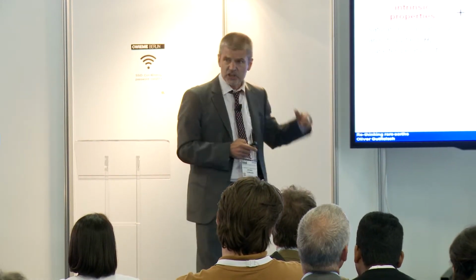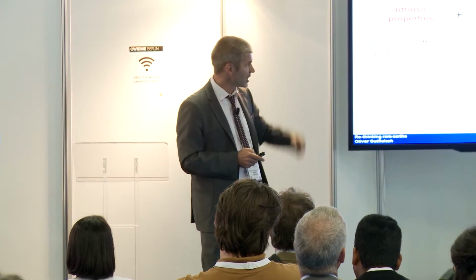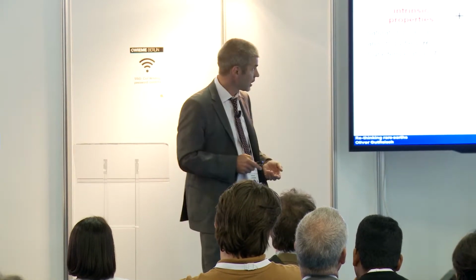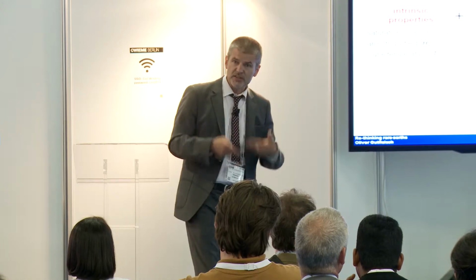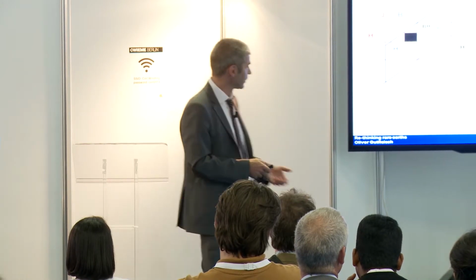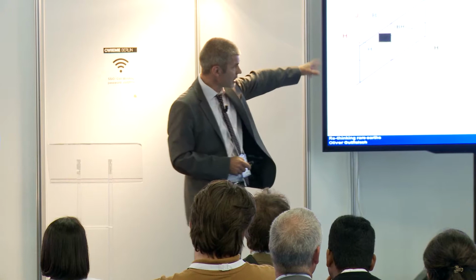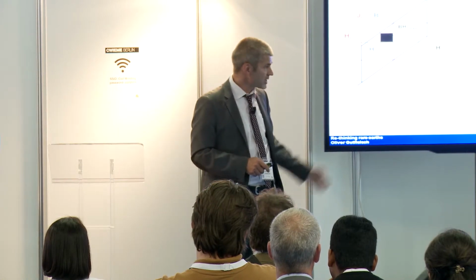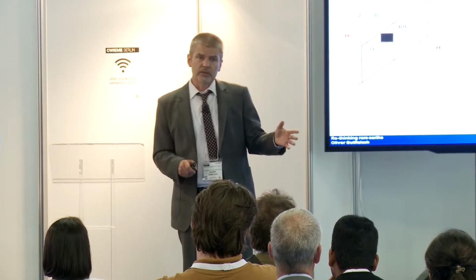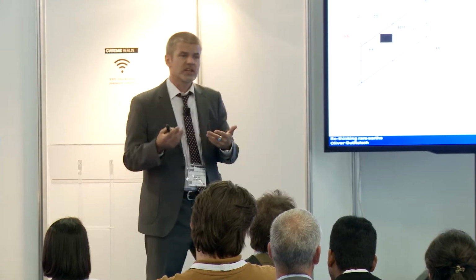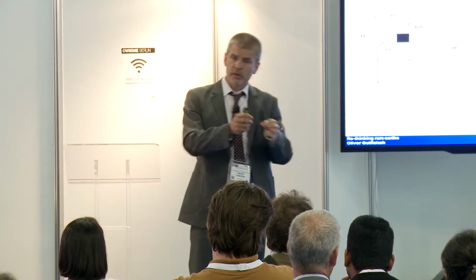And then we start engineering the microstructure so that we have extrinsic properties, remanence, coercivity, and energy density, that we can use. And this is then plotted here in the hysteresis graph. You can see on the right-hand side how this has developed. And let's say, in a way, sadly, we are stuck since 30 years with neodymium iron boron.